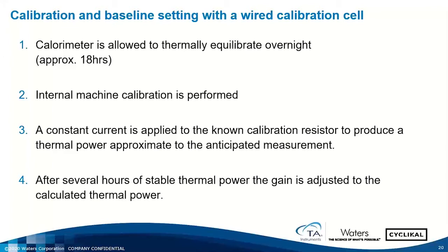So the first thing we do, after the calibration cell is inserted, we allow approximately overnight for thermal equilibrium. We then do an internal machine calibration, and that sets a gain and a baseline. After that internal machine calibration is finished and we're back to a stable thermal power, we'll then apply a constant current to the known calibration resistor to approximate a thermal power of where we're going to work in the real experiments.